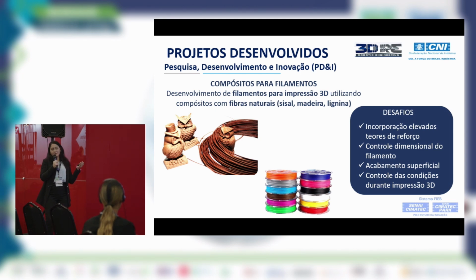So we've developed composites for filaments for 3D printing. In this case, we added sisal, wood, and lignin fibers in a polymeric matrix. We tried to incorporate as much filler as possible to obtain filaments that can be truly used in manufacturing and in 3D printing. Well, challenges.